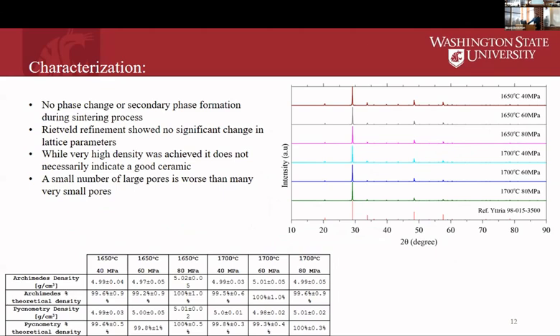We knew that we had some rare earth contamination. We were curious if that rare earth contamination would precipitate out and form a measurable secondary phase, but we noticed it didn't. When doing our density measurement, we measured it two ways: by pycnometry with a helium gas pycnometer, and also with water displacement, Archimedes-style density. We found very good agreement between these two numbers, which tells us that our porosity is likely closed off, so neither water nor helium is able to get into our sample where the actual pores are.